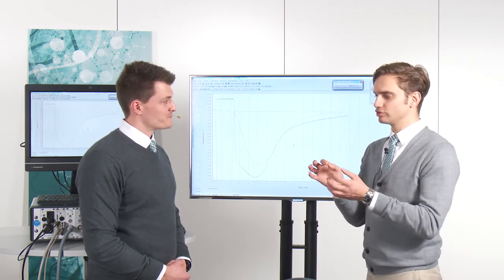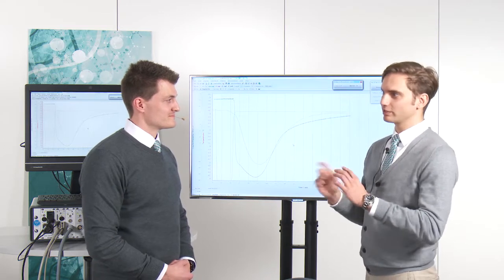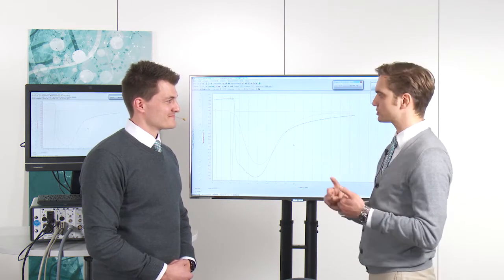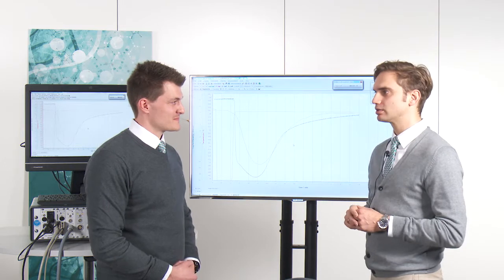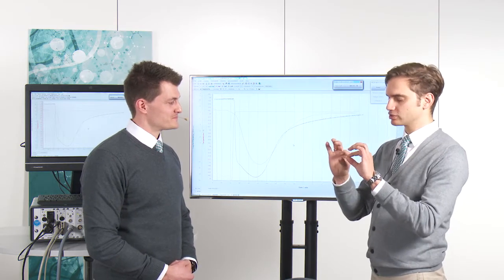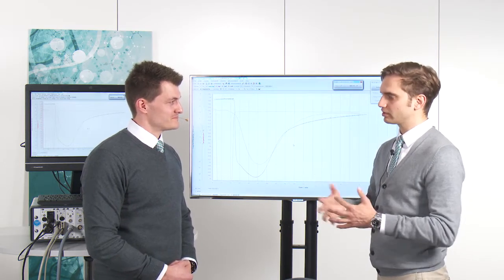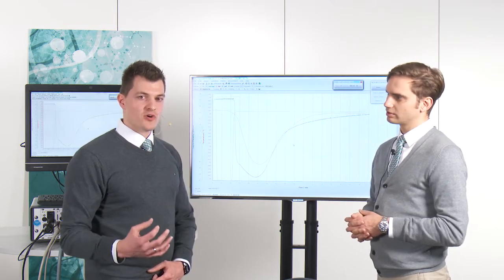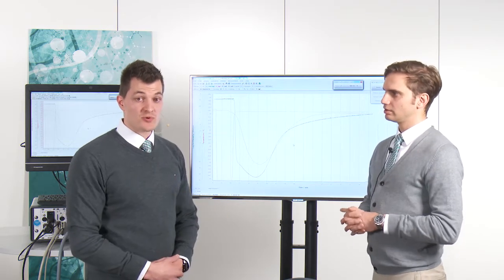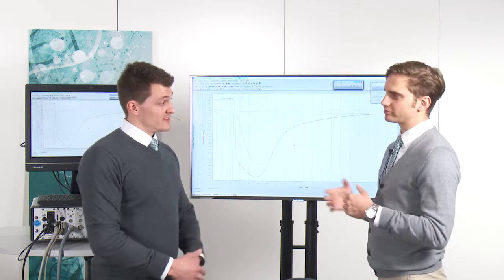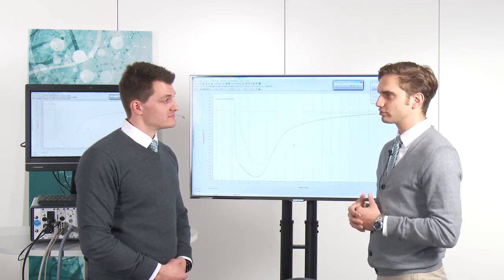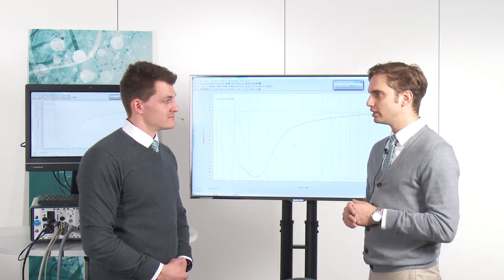You just have some black disk and put it in the machine, and that went really fast. So first question is, how did you prepare the sample? Because normally I would think this is just a one-layer prepreg. So how did you? Yeah, we used 24 layers of this unidirectional carbon fiber prepreg from SGL. Okay, so that's quite a representative sample, I would say, for coupon testing, as you would do in the lab.